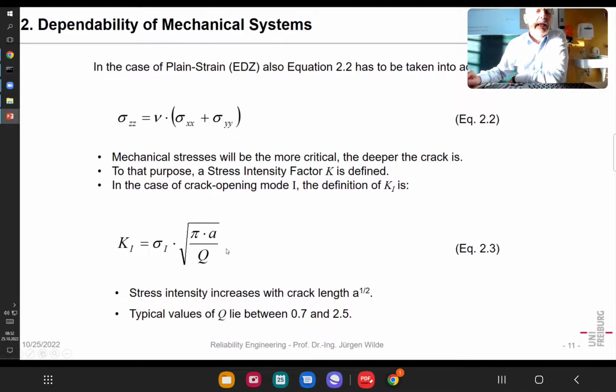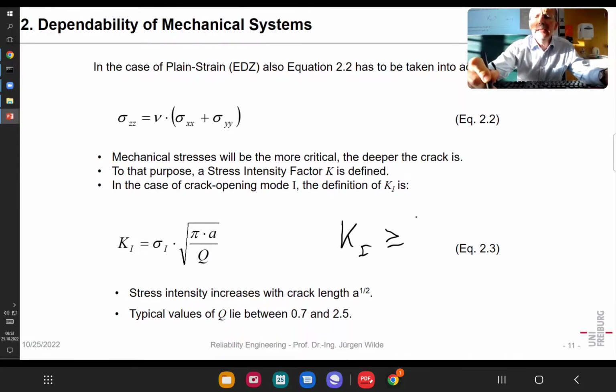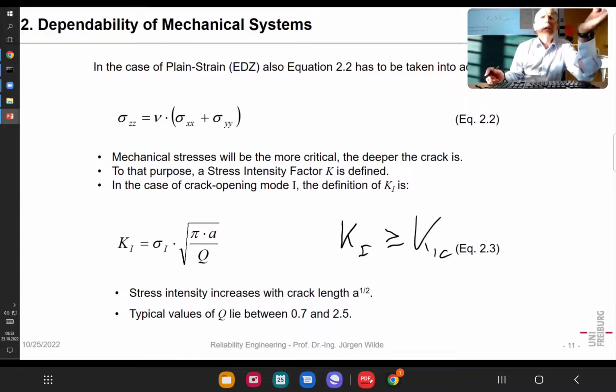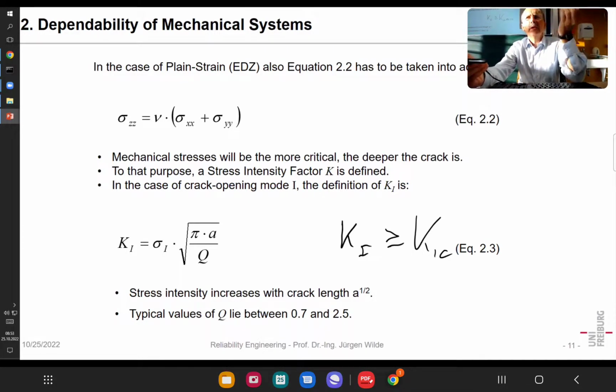And in that way, we have another failure criterion. Normally we say when the normal stress is higher than the ultimate tensile stress, then it will fail. But if it's a part that has a crack, then the part will fail when the K1 factor is larger or equal to the K1C factor. Ultimate tensile strength is a material property. And the K1C, you can call it the critical stress intensity, but it is also called fracture toughness. That's a material property. So again, you have a criterion: is the load higher than the strength, it will fail.